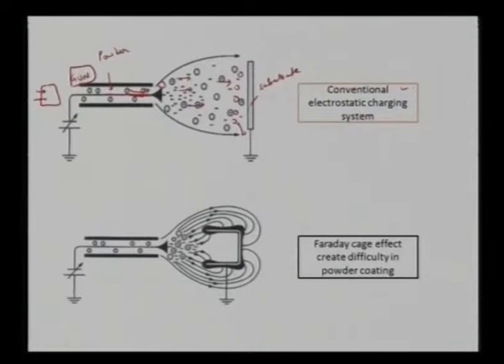Again, this is one of the very simple processes. We apply a certain voltage here, and that voltage is carried by the electrode, which faces the front portion of the electrostatic spraying gun. The blower allows the powder particles to flow, and as they flow they get charged because they interact with the electrode. Once they strike a substrate, the repulsion between the powder particles, because of the similar charges, creates very nicely dispersed powder particles